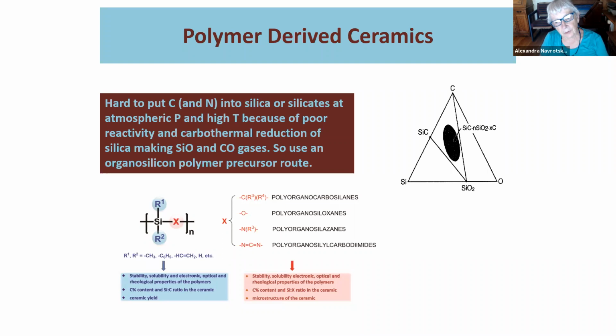And that indeed has worked and has gotten the whole field of polymer-derived or polymer precursors for all sorts of interesting inorganic materials, for organic-inorganic composite materials, and so forth. The polymer-derived ceramics, classically in the silicon-carbon-oxygen system, or the silicon-carbon-nitrogen system, or the silicon-carbon-nitrogen-oxygen system, have been studied extensively, and one has also been able to put other metals into them. And these materials have very interesting properties.